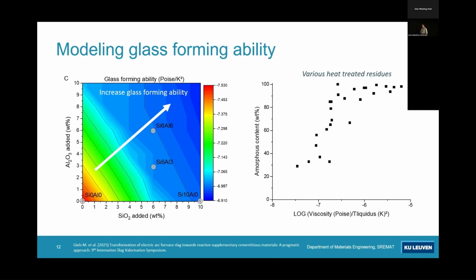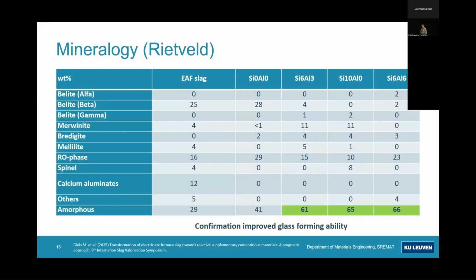However, we know it's very difficult with steel slags to do this. We have to add a lot of fluxes. So we will be somewhere around 60% amorphous, so around -7 to -6.5 with respect to glass forming ability. So we did these tests using this new parameter to guide our experiments. We chose some experiments, which you saw as indicated on these heat maps. And we found out indeed that if you add silica and alumina as predicted with that formula, you can create more amorphous content, which is in line with what we expected based on our plots, that we could get around 60% amorphous.